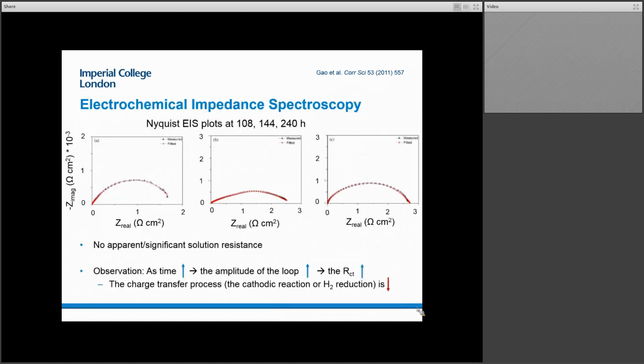I've chosen this example because it is a digestible system that will allow you to make the translation from that simple model. So in this test, they looked at those three time points: before, during, and after that resistance change. You can see they're certainly not semicircles, but they have the flavor of it. As time increases, we see the amplitude of the loop increasing, i.e. the impedance in the real direction. What that implicates is that the resistance to charge transfer is increasing, i.e. the charge transfer process is being held back.